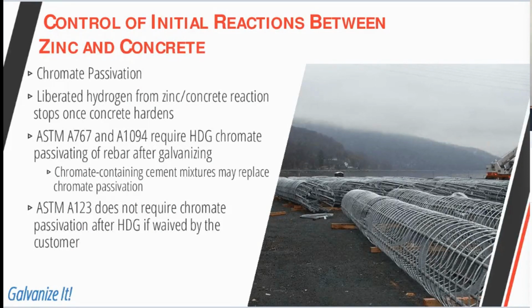There are requirements related to chromate passivation after galvanizing, and this is a process used to control initial reactions between zinc and concrete, which could interfere with the bond strength or overall longevity of the rebar. ASTM A767 and ASTM A1094, they do have requirements for chromate passivation after hot dip galvanizing in order to limit these types of reactions. However, these requirements could be waived. And in fact, many domestic supplies of cement mixtures already have sufficient chromates to limit these reactions from occurring.